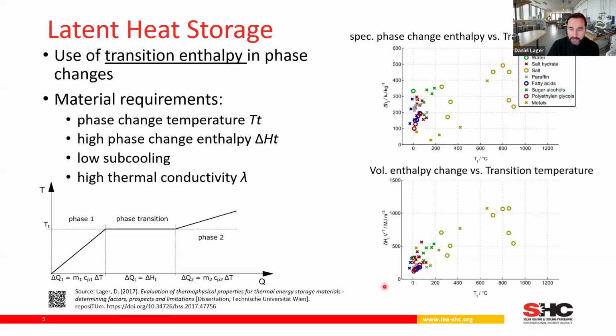On the picture here on the bottom, you see the same materials again, but listed over the volumetric enthalpy change. And here you see, for example, that salts have a really high volumetric energy density at high transition temperatures in comparison, for example, to salt hydrates or paraffin waxes.